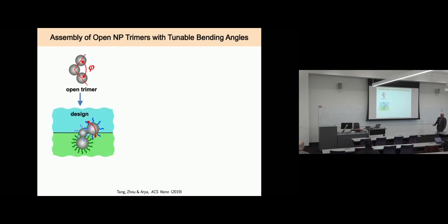Okay, so our idea was if you could trap one particle at the center, okay, by either choosing a neutral particle or grafting it with neutral polymers that are neutral to the 2 fluids, trapping another particle well below the interface with a lot of grafting so that you can push this to an almost 90-degree angle, and then using the grafting density on the other particle, which has the polymer that likes the other fluid, and tuning that grafting density to change the angle.